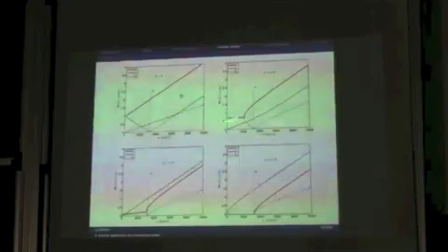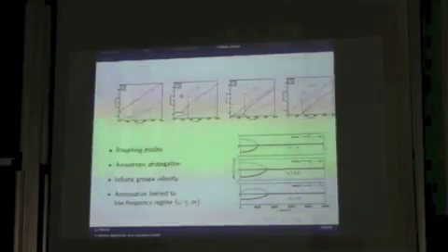Here what I have shown you is the real part of the wave number, but in fact the wave number is complex. What you see here vertically is a situation where you have a zero group velocity. That means that the energy does not propagate. What you see here is something that I don't really like. It's a situation where you have an infinite group velocity, which is something special. But in fact, this term here is related to a complex wave number with a non-null imaginary part.